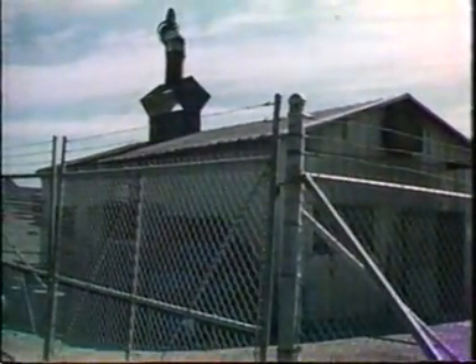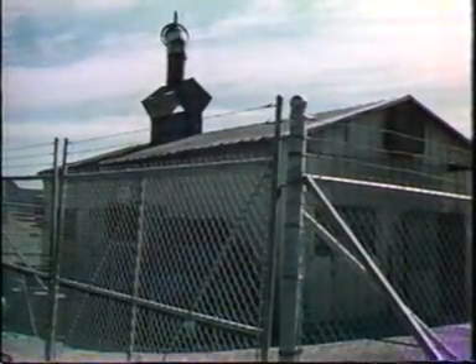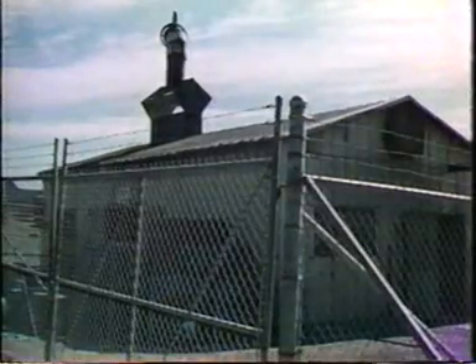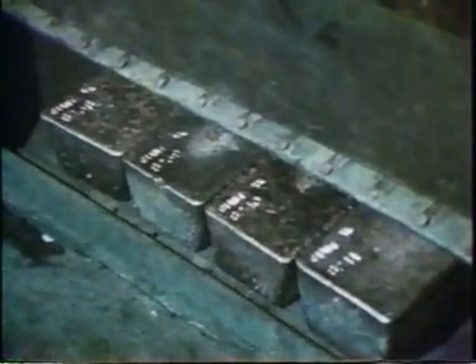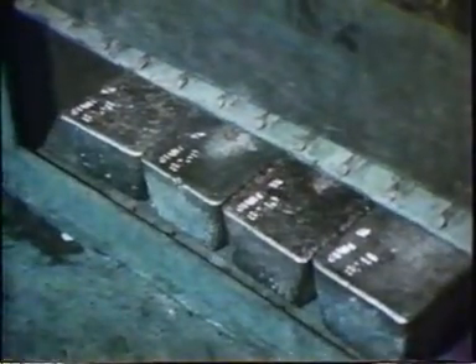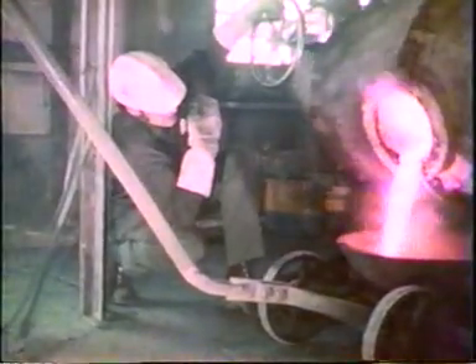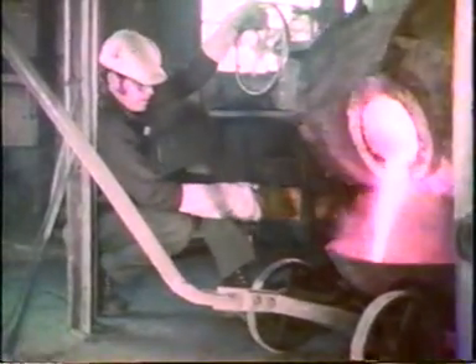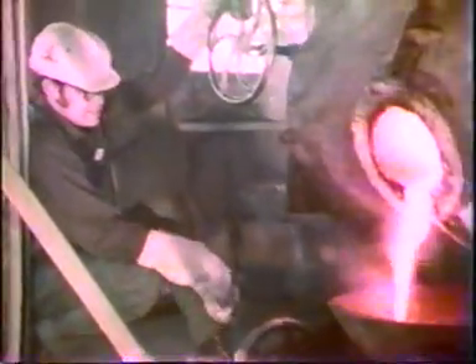After the cyanide process, which succeeds the crushing, the ore arrives here in the form of the precipitate from the cyanide process. And here the ore is finally refined and turned into the gold bricks that we would all like to have at home. The first stage is to put the precipitate into small furnaces, and when it's molten, to draw off the slag, or most of the slag. It's impossible to perfectly separate the slag, which is formed by the fluxes that are mixed with the precipitate from the cyanide process, but most of it can be removed in this fashion.